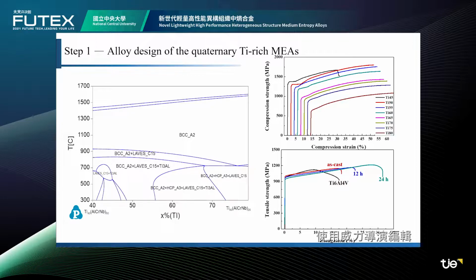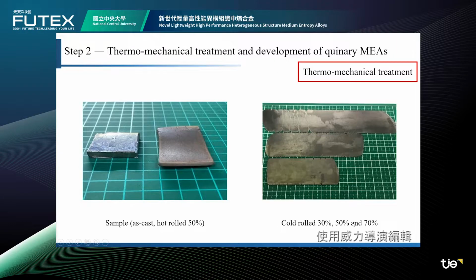On the other hand, for structural materials, the tensile properties are more critical than compressive properties. Among titanium 45 to titanium 80, titanium 65 presented outstanding tensile properties. The strength can reach 1,200 megapascal, and the ductility is 80%. Moreover, after homogenization heat treatment, the plastic deformation can be enhanced to more than 30%.